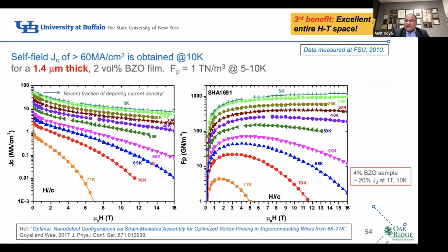The third very exciting thing that happened was that when we cool these materials down to low temperatures, these columnar defects are only supposed to provide us good performance and pinning of the flux line lattice at higher temperatures. It turns out we got at 5 Kelvin a record fraction of the depairing current density for the very first time. Highest performance ever reported originally.